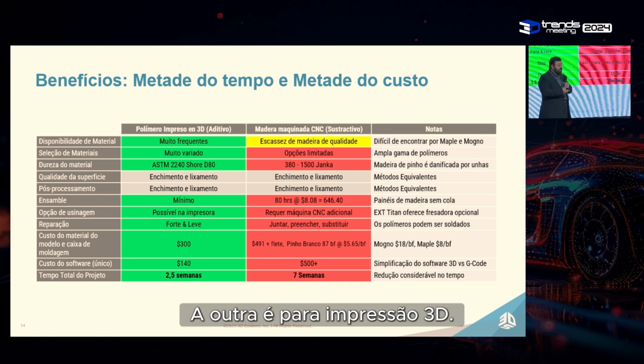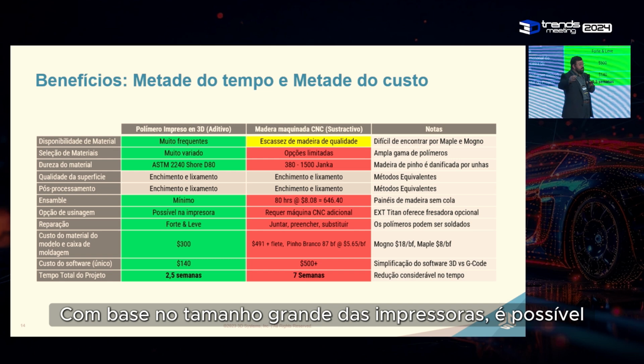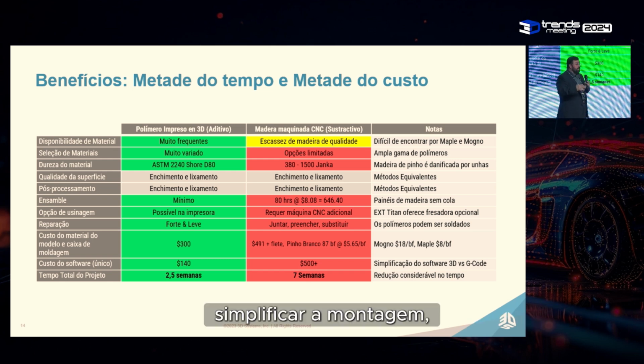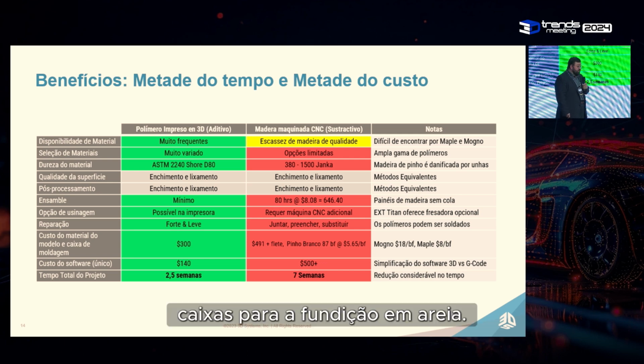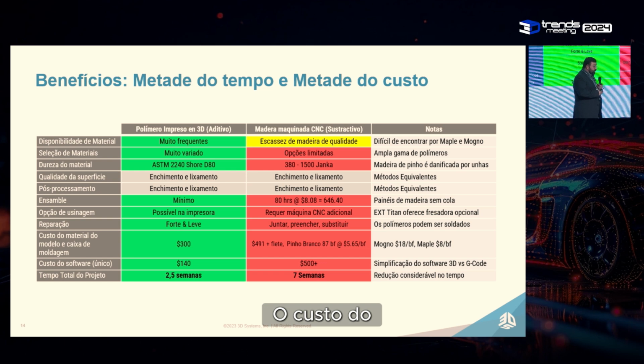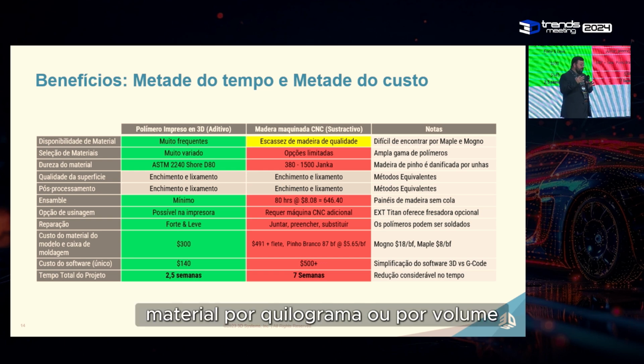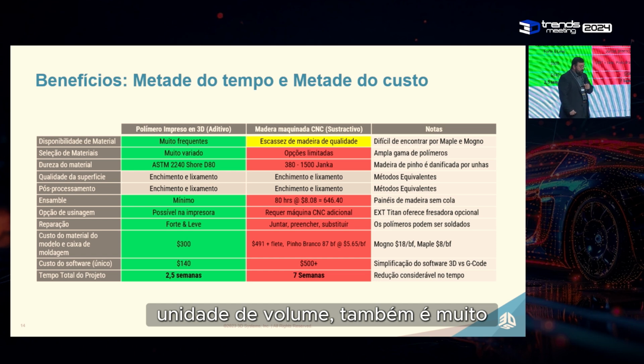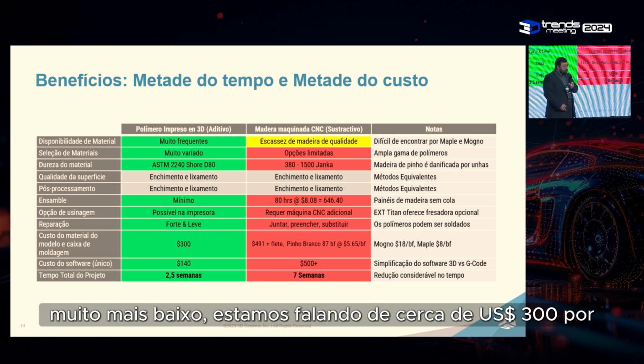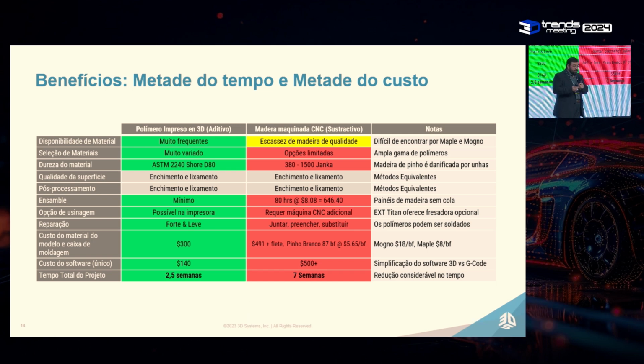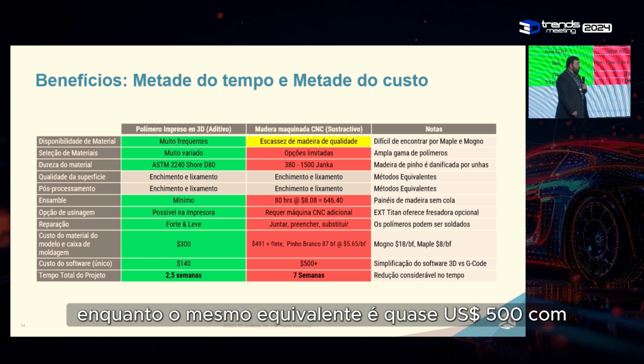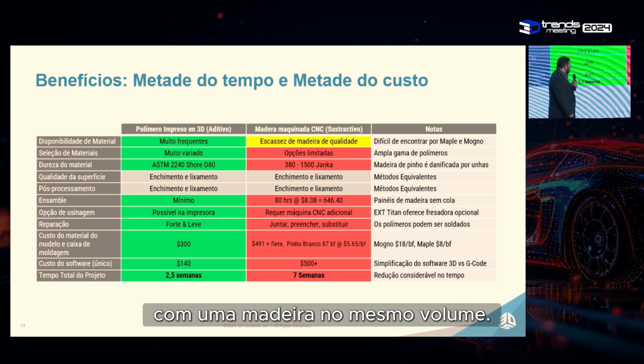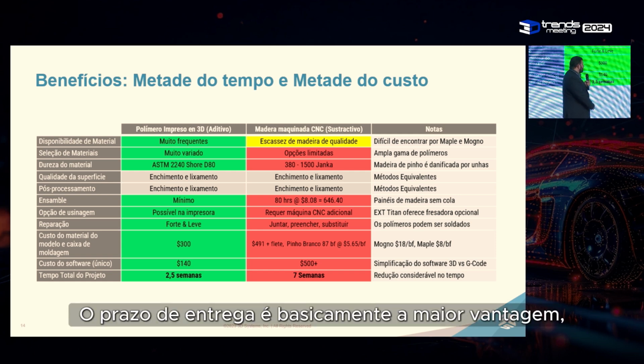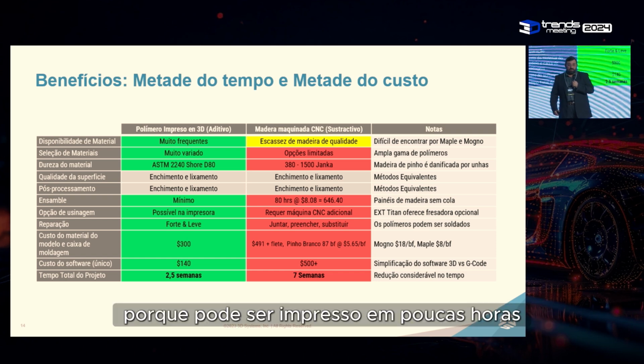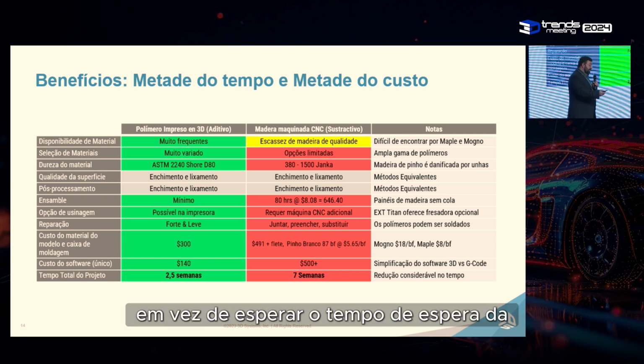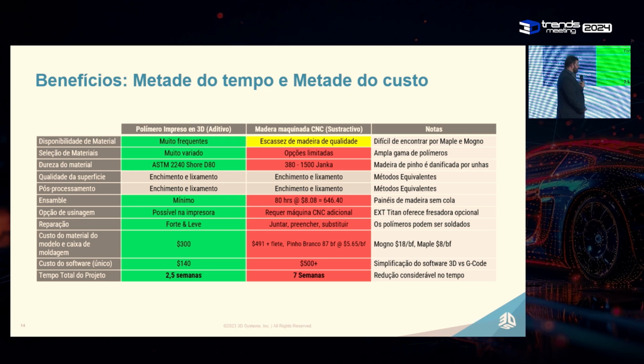The other is that 3D printing, based on big size printers, can simplify the assembly or the process to create the whole boxes for the sand casting. The cost of the material per kilogram, or per unit of volume, is also much lower. We are talking about something like $300 for a box, while the same equivalent in wood is almost $500. The lead time is basically the major advantage because it can be printed in a few hours instead of waiting for the lead time of the wood.